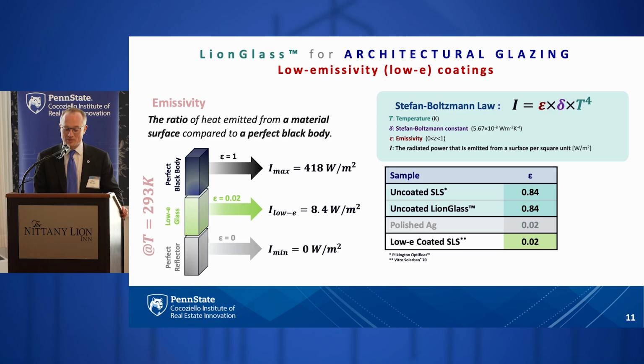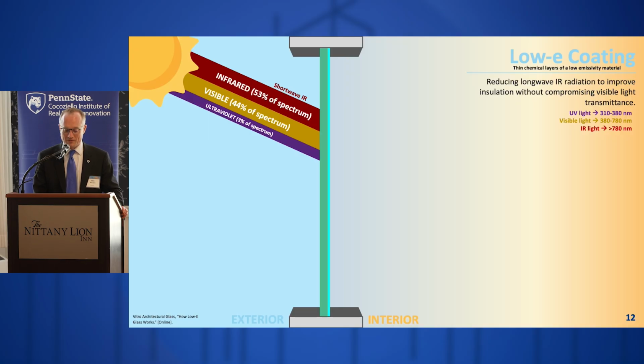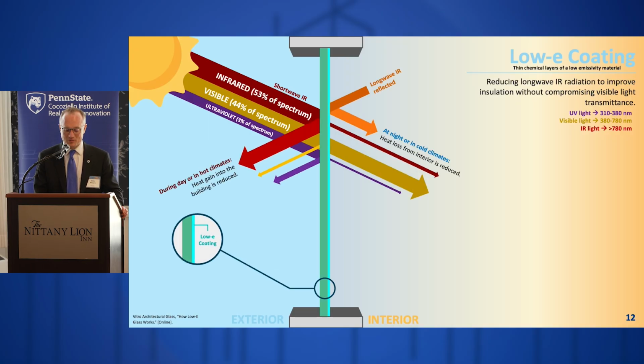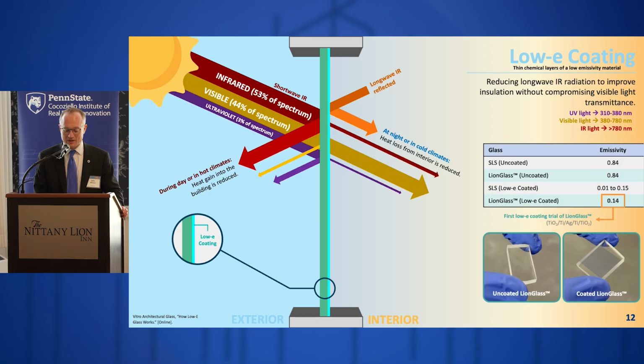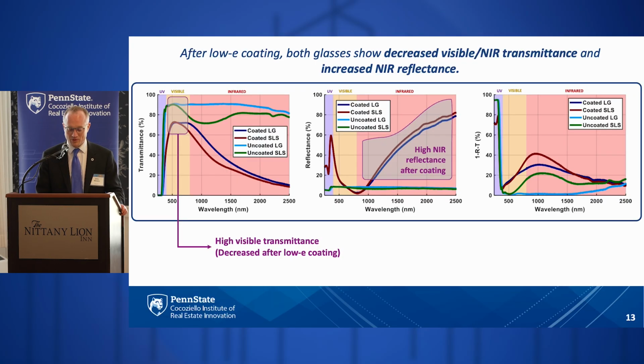And then the next question is, what about coating? The low E coated soda lime silicate brings the emissivity down significantly. We don't have the complete professional setup to do that here, but we were looking at applying some low E coating manually. You can see on the lower right, this shows uncoated LionGlass versus coated LionGlass. You can see a little bit of the coating there, and you can see in the table that the LionGlass with low E coating has an emissivity of 0.14, which is within the range reported for soda lime. And so we were very happy with that progress there as well.